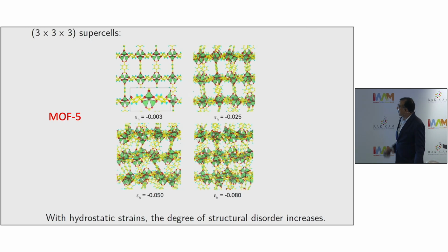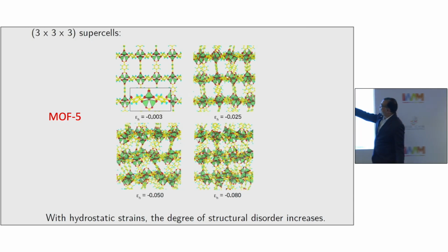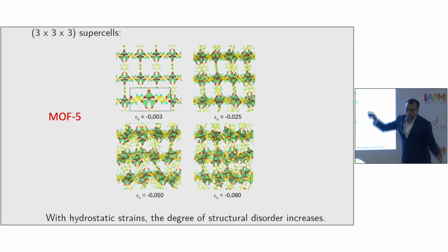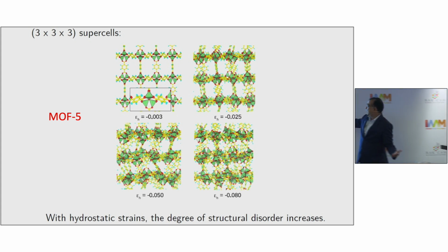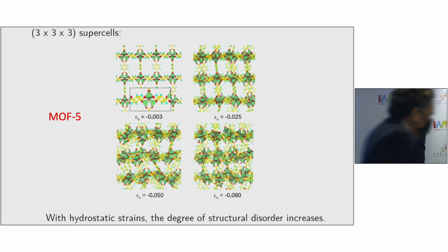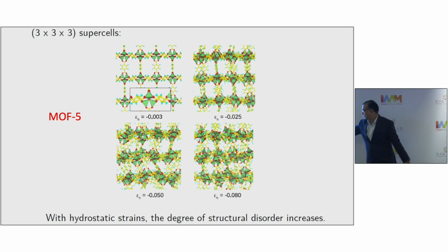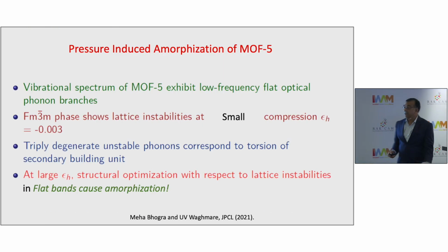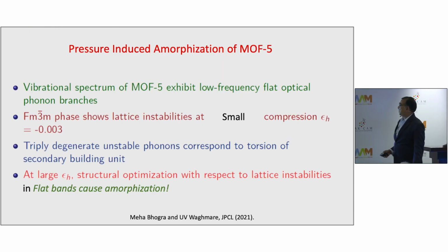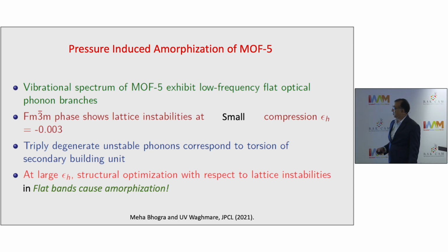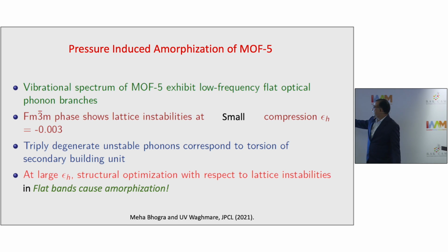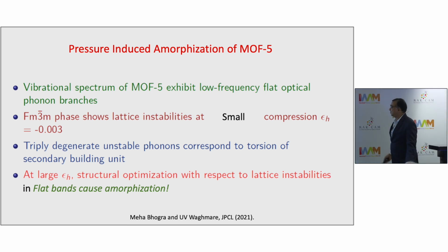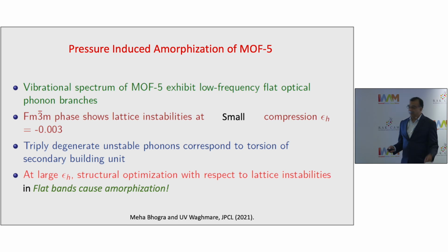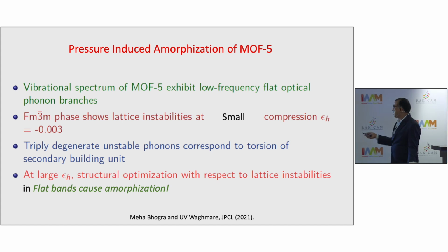Okay? And this is the picture. You start from a beautiful crystalline form of MOF5, and then we consider a superperiodic structure and allow for distortions which lower the symmetry, and basically you develop an amorphous phase at low pressures. So let me summarize. The vibrational spectrum exhibits low-frequency flat optical phonons, and at very small compression you get unstable modes which constitute flat bands of phonons, and then any combination of those unstable modes is equally likely to destabilize the structure, and that's how you get amorphization through a disordered state.